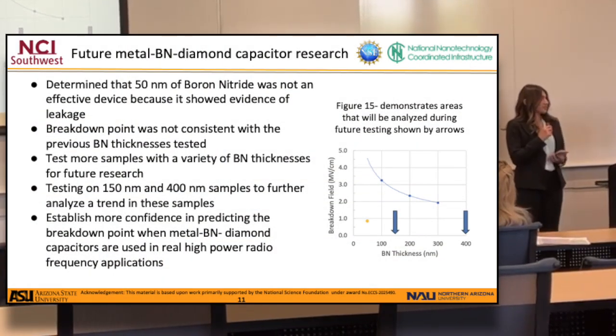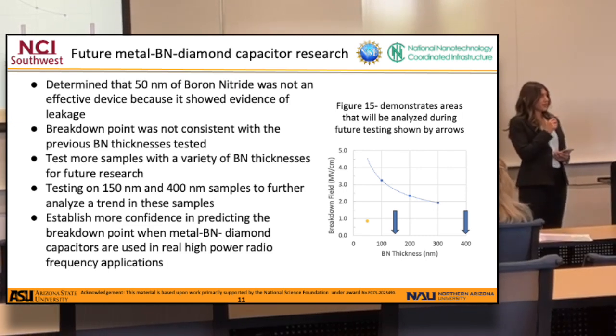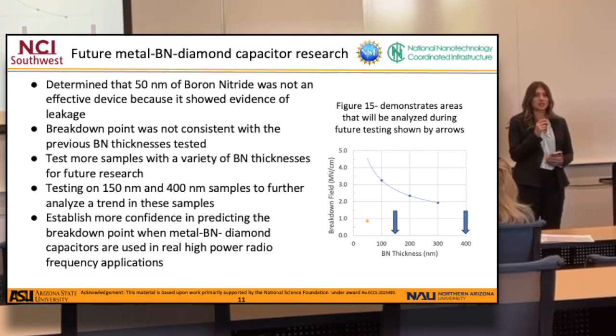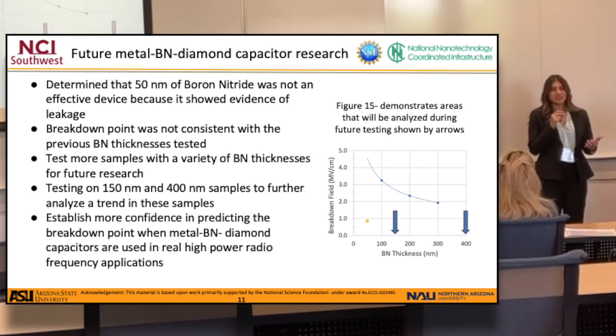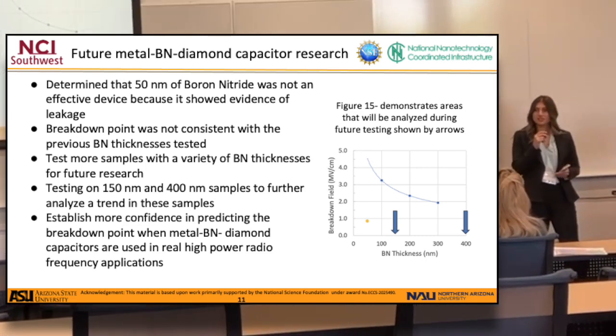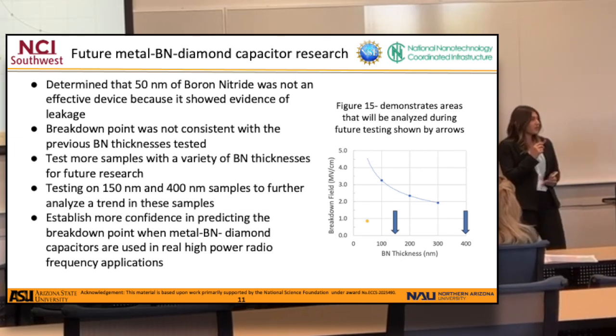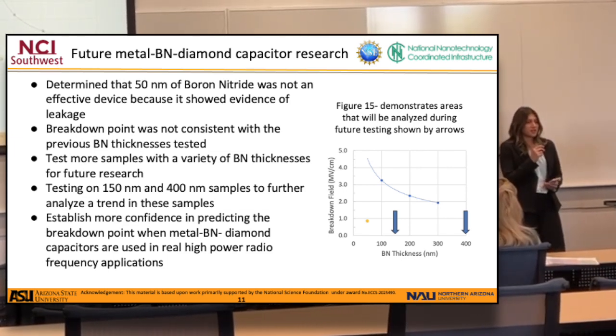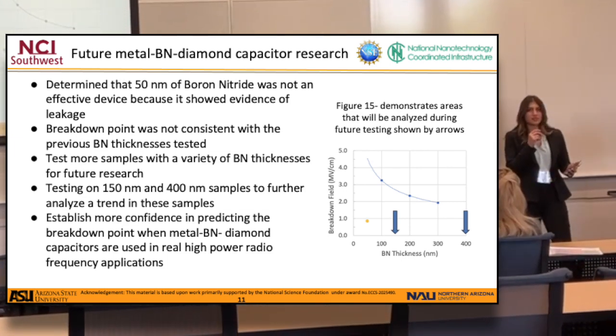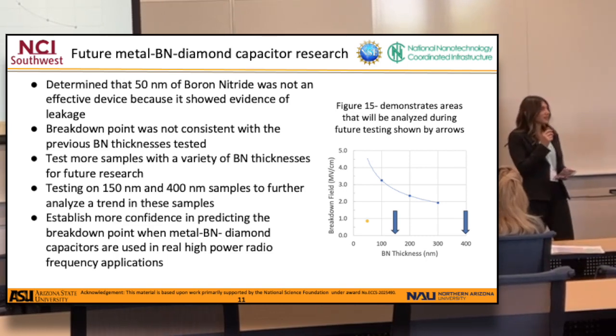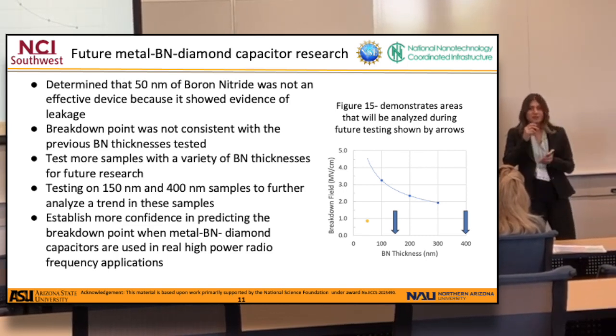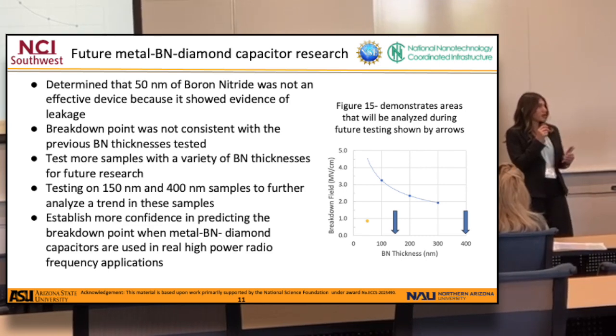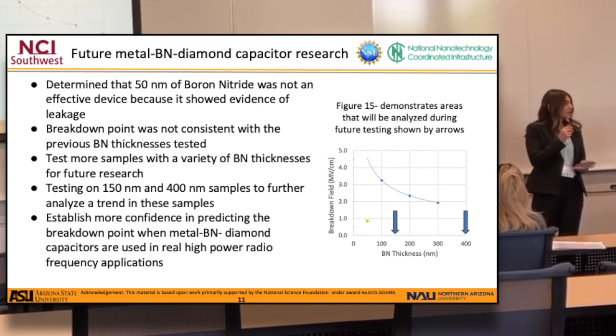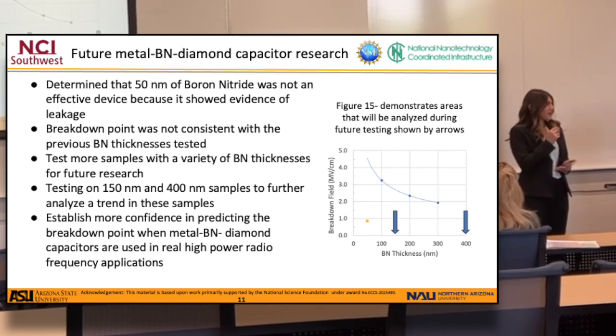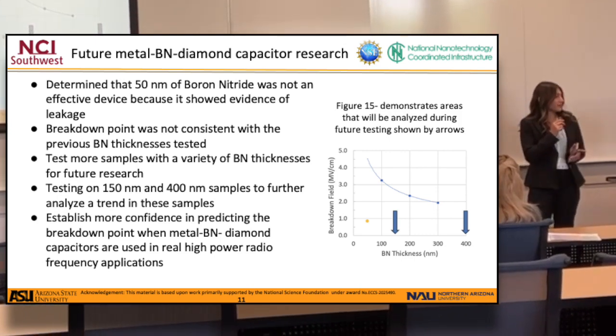In conclusion, my research determined that 50 nanometers of boron nitride was not an effective device because it showed evidence of leakage, and it wasn't exactly consistent with our previous research that we tested. And so in the future, we want to test more samples with a variety of boron nitride thicknesses and plot them on our curve so we can have more confidence in predicting the breakdown point when the metal boron nitride capacitors are used in real high-power radio frequency applications.